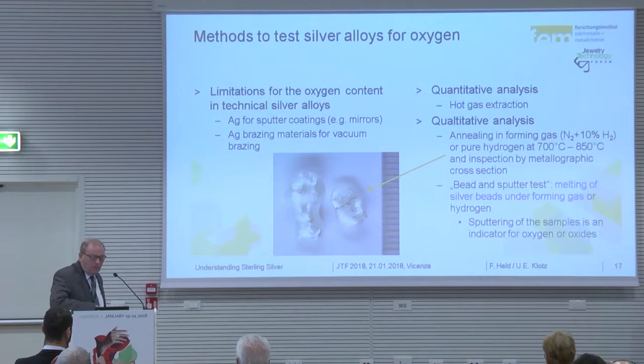This is the method to measure oxygen in silver. We have annealed these granules in forming gas, which contains 10% hydrogen. We do the annealing at about 700, 800 degrees, and we have inspection by metallographic cross-section. We also know bead and sputter tests, something out of the industry. If you use special soldering material, which is silver copper at the eutectic phase, they do annealing under forming gas or pure hydrogen and look if it sprays. And if a sputtering of silver is in the area, they know oxygen is inside.